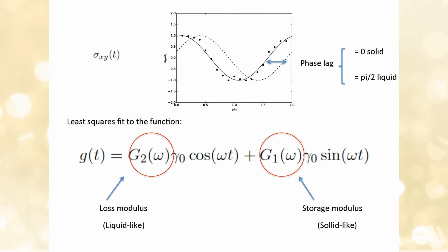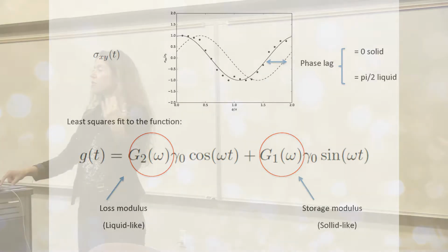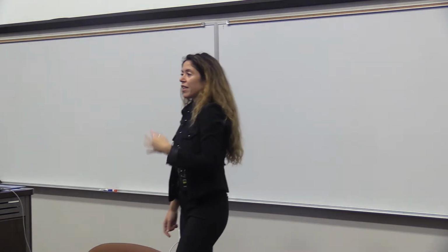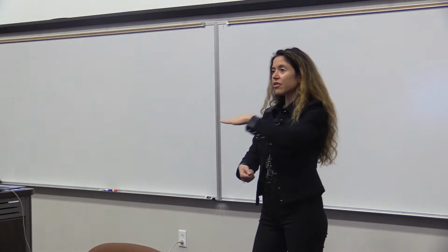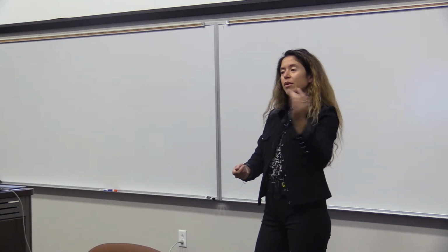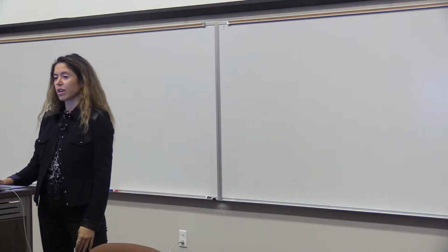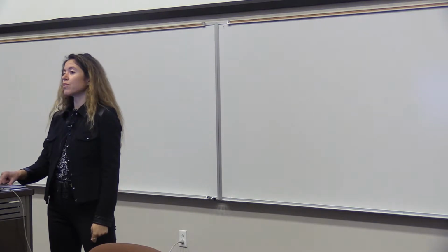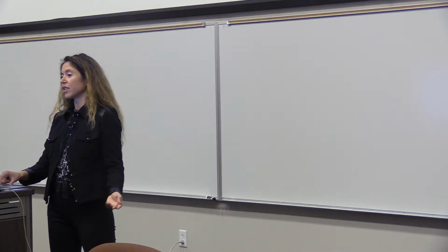If the phase lag is 0, your material would be a solid, and if the phase lag was pi/2, that would be more representative of a liquid. The idea is you move this object. If it is a solid, everything will move wherever you take it. But if it is a liquid, there is of course freedom for the molecules to move wherever they want.